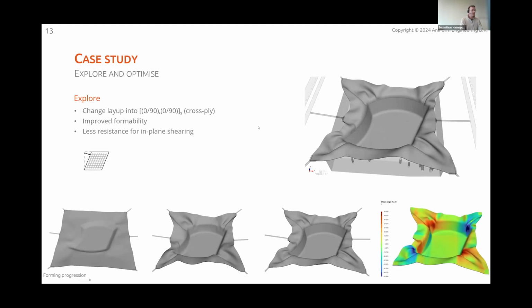And that is mostly because there's less resistance against in-plane shearing. We don't need all that friction between a 0/90 and a 45 ply in this case because of the absence of it. And this shear is plotted in this image as well. We see a lot of in-plane shear in the corners. And that's what you really need to have good formability when forming this kind of deep part.